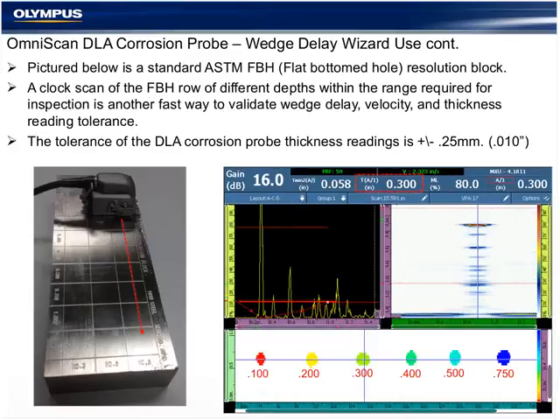A similar standard function would be to use the ASTM flat-bottomed hole resolution block. This is a standard common calibration standard that you would see in any NDT supplier's catalog, and it contains a series of flat-bottomed holes of different size and different depth within the block.